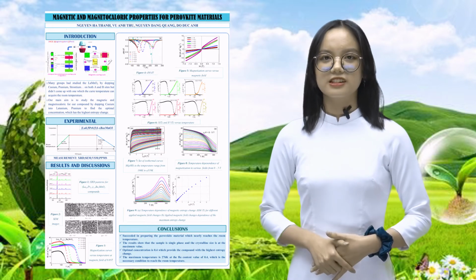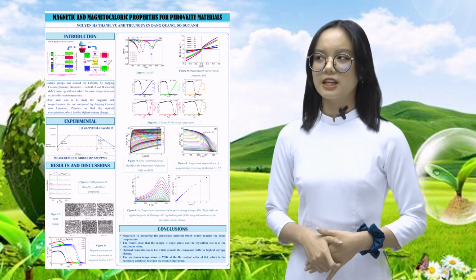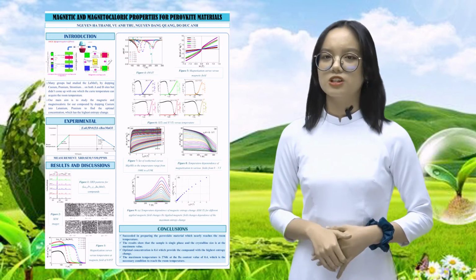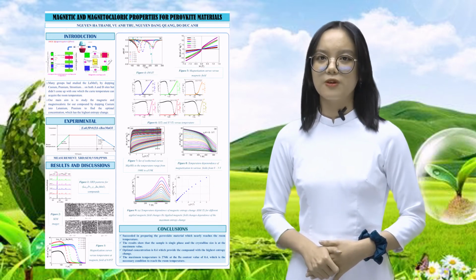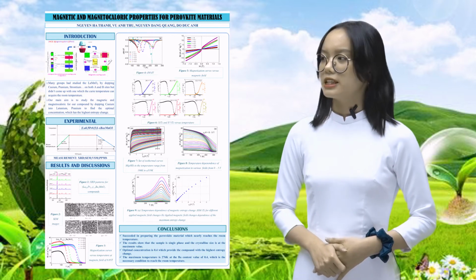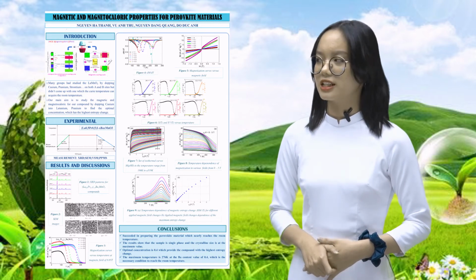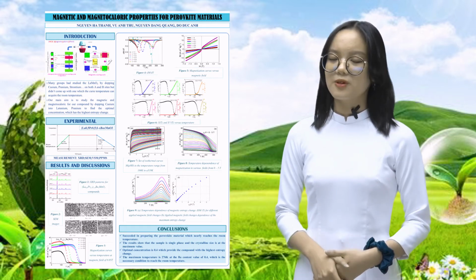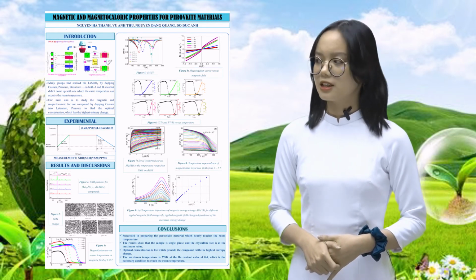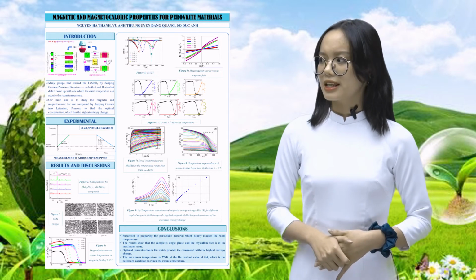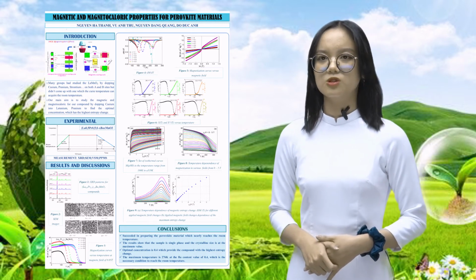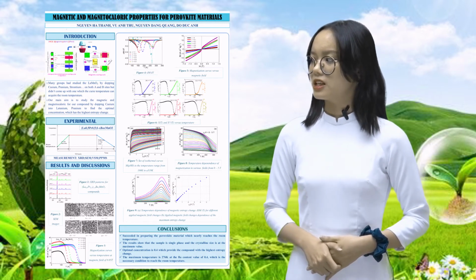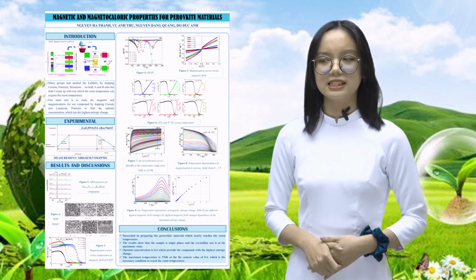Now move to Figure 7, which provides the set of isothermal curves in the temperature range from 100 Kelvin to 319 Kelvin. Magnetic values show a large variation in intensity around the Curie temperature. At the lowest temperature and low magnetic field, the magnetization increases strongly and tends to saturate when the magnetic field is larger than 1.5 Tesla.